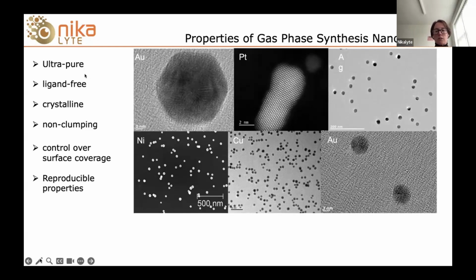They're ultra pure, there's no contamination. I've mentioned that no chemicals are required. There's no surfactants. There's no agents required to keep the nanoparticles dispersed. So in these images, you can see we've got non-clumping. Clumping is a real problem in chemical synthesis, whereby the nanoparticles will form in solution, but they just want to stick together. So surfactants are added to that process to keep them from clumping. That's not needed with gas phase synthesis. The nanoparticles are naturally dispersed and they land on the surface and they'll stay where they land.